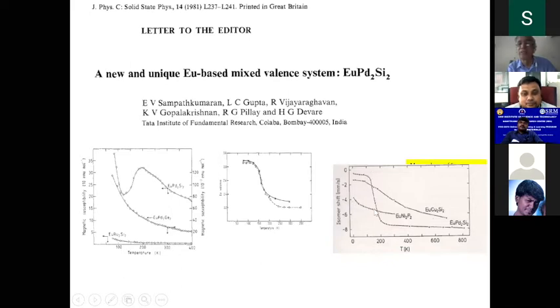We discovered another material where you see a weaker valence change, which still remains intermediate valent even at low temperature. In this case, it goes almost 2+, almost 3+. It never reaches complete integral valence. It reaches fractional even at this temperature. Here it remains truly fractional, completely intermediate. These are some of the very unique systems which people in the field still study even after 4 decades. And look at the susceptibility, a very huge change, the peak here, because you're going from almost 2+ which is magnetic to almost 3+ which is non-magnetic. This is due to impurity here. This is one of the most exotic papers which I published, and it is very well cited.